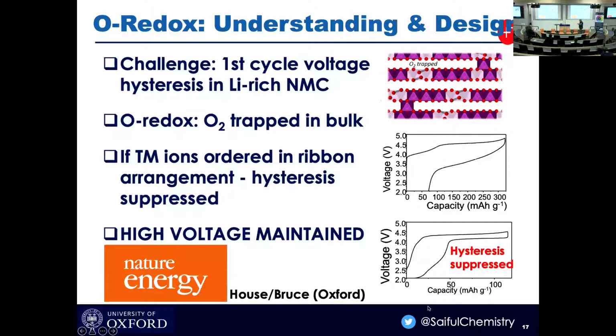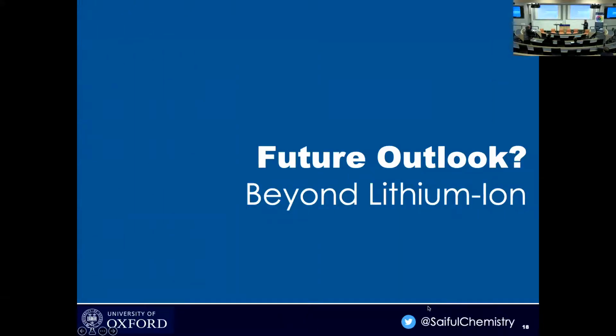But they found that if you look at different structural rearrangements, you can mitigate that voltage drop. That's shown in the plot on the bottom right: the voltage drop is much reduced, that hysteresis is much suppressed, i.e. the high voltage is maintained, that high energy density. The next step is trying to get this for multiple cycles, but this is really showing that fundamental underpinning science. Once you begin to understand what the problem is, you can begin to mitigate those challenges. And that's published in Nature Energy. So that's work coming straight from the Oxford group. So what's the future outlook?